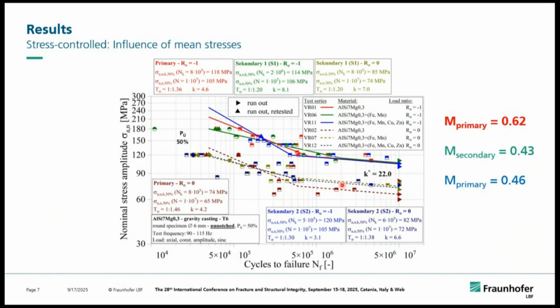What we could see beneficially is that when we come to the secondary 1 and secondary 2 alloys, sorry, there's a mistake, we got a loss in the mean stress sensitivity, which is beneficial on the one side. And looking at, for instance, the secondary 2 alloy, we had a lower slope in the medium cycle fatigue range, which is also beneficial when it comes to damage sum accumulation.